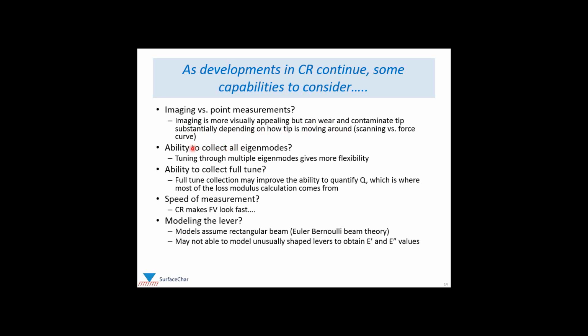Another important capability is your ability to collect all your eigenmodes. Just like the freely vibrating cantilever has multiple vibrating eigenmodes, in contact resonance we also have multiple modes corresponding to those. And the ability to tune through multiple eigenmodes gives you more flexibility and improved sensitivity, because sometimes some modes are better than others. Another important capability is the ability to collect your full tune. Some techniques rely on collecting parts of the tune or sampling at different points, but a full tune collection will improve your ability to quantify that quality factor, which is especially important for that loss modulus calculation.